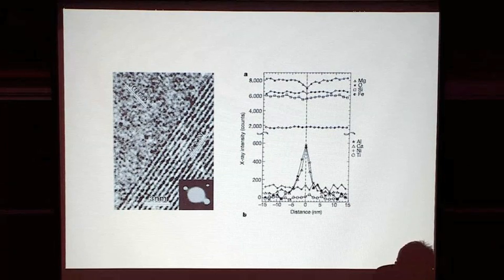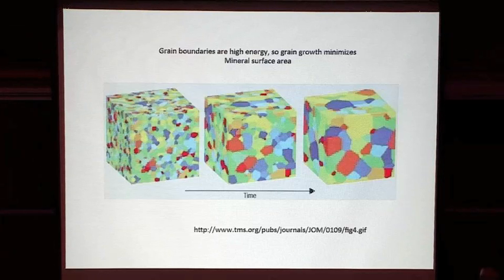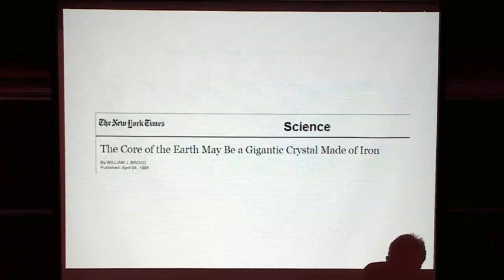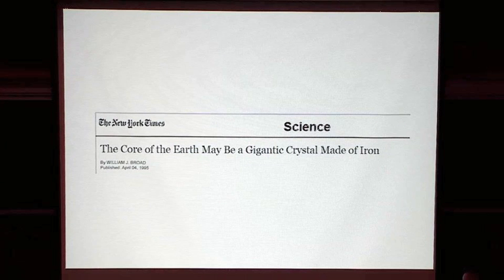So that's just a simulation illustrating that with no particular physics behind it. And so you might think, well, that's great. We should end up with really large grains. And Bill just suggested perhaps that we could have meter-sized grains in the lower mantle. If we take this to its extreme, and actually this was motivated by something else, we may think the inner core. Grain growth in metals is incredibly fast, and the inner core is really hot. Actually, this article was not motivated by that. But how come grains aren't really huge in the mantle if the system wants to get rid of grain boundaries and grain growth is so favored?